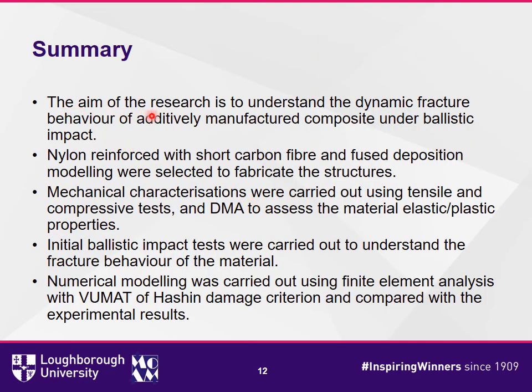So to summarize, the aim of the research is to understand the dynamic fracture behavior of additively manufactured composite under ballistic impact. Nylon reinforced with short carbon fiber and fused deposition modeling were selected to fabricate the structures. Mechanical characterizations were carried out using tensile and compressive test, including DMA to assess the material elastic-plastic properties. The initial ballistic impact tests were carried out to understand the fracture behavior of the material. And finally, numerical modeling was carried out using finite element analysis with the VUMAT of Hashin damage criterion and compared with the experimental results.